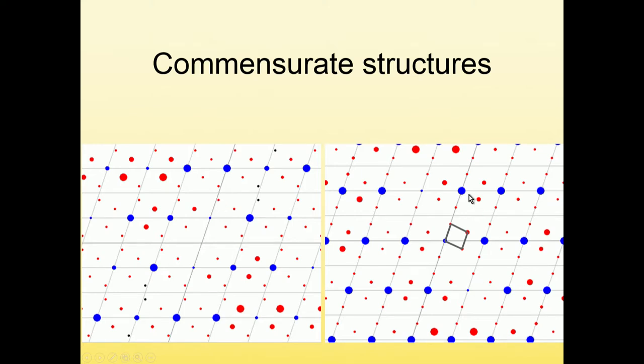This here is the diffraction pattern of the same material cooled down by about 50 degrees, or 50 Kelvin. And you see that the distribution of the positions is very similar. You still have the same average structure. The satellites are almost in the same positions, but now let me take this place. So first order satellite, second order satellite, but now this satellite lies exactly on this line, and it is also exactly in one third of the distance from here to here. So the components of this satellite are actually minus one half, one third. So this is commensurately modulated.